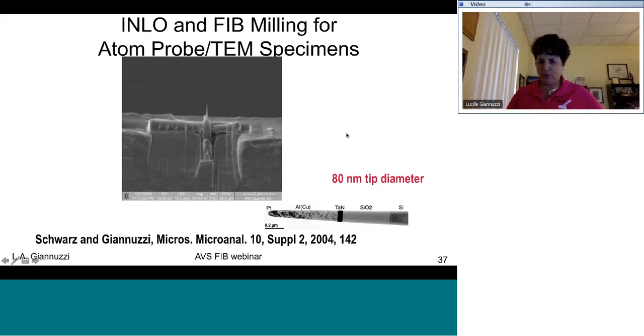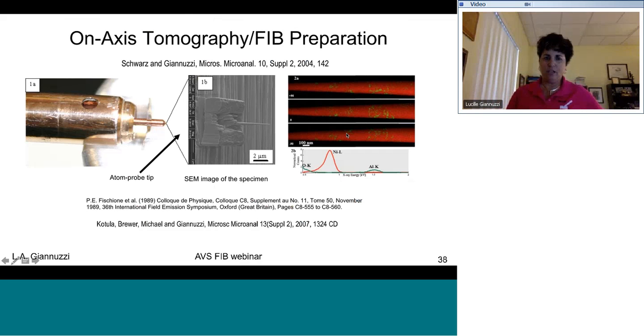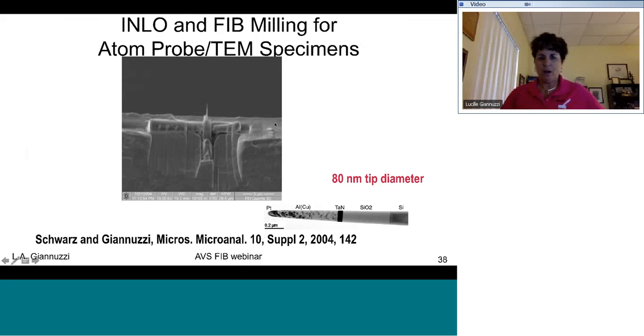And then, of course, you can take these, sorry, let me back up again. By virtue of the size of these atom probe tips, they also happen to be electron transparent. And so it's often useful and in some cases necessary to take a TEM image of the sample before you do the atom probe work so that you can correlate your atom probe results to the structure that you see in your TEM results.